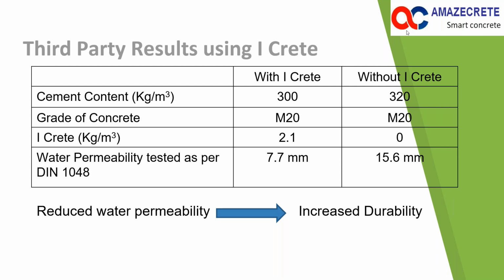So when we are talking about advantages of using this product, the most important advantage is, even though we have reduced from 320 kgs to 300 kgs, there is a tremendous reduction in the permeability as per DIN 1048. So almost 50%, less than 50%, means tremendous reduction in the permeability has taken place. As we know, reduced water permeability means increased durability. So this is the added advantage of using this product, even though we have used a lesser amount of cement or cementitious content.